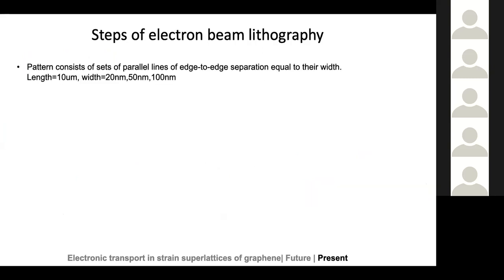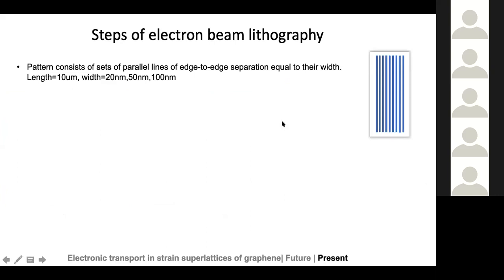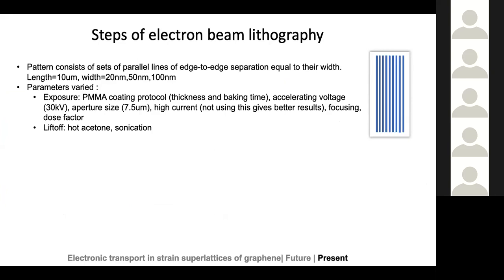So my pattern consisted of this set of parallel lines, and essentially the electron beam will expose over each of these lines. They were 10 microns, and we varied the width of these lines between 20 to 100 nanometers, because if you remember, if the features are wider than 100 nanometers, there isn't enough strain left in the system to see any effects.